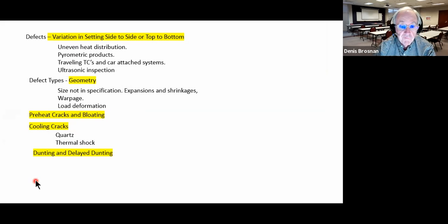So here's a very brief listing of defects. Variation in kilns side to side and top to bottom. Uneven heat distribution. Well, how do you know if you have uneven heat distribution? Well, one way is testing the product itself. It's going to tell you that. And in fact, I've mentioned to you before that I know of one plant in North America that uses ultrasonics, or velocity of sound, on kiln cars as they exit, at just a few selected brick positions in a brick plant, to tell if the heat distribution is even.